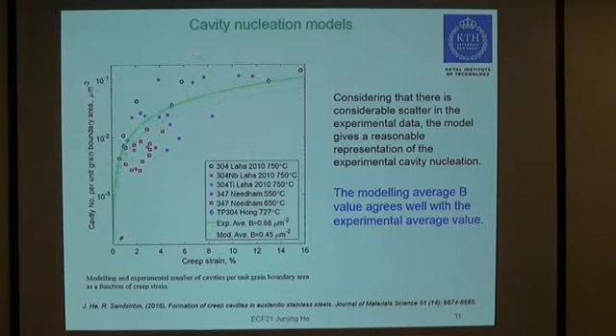Here are the results for the cavity nucleation models. This figure shows the cavity number per unit grain boundary area as a function of creep strain, for different types of austenitic stainless steels. The lines here are the modeling results, and this is the experimental average values. It's very evident that there is considerable scatter in the experimental data, but the model still gives a reasonable representation of the experimental behavior. The modeling average value also agrees well with the experimental average value.